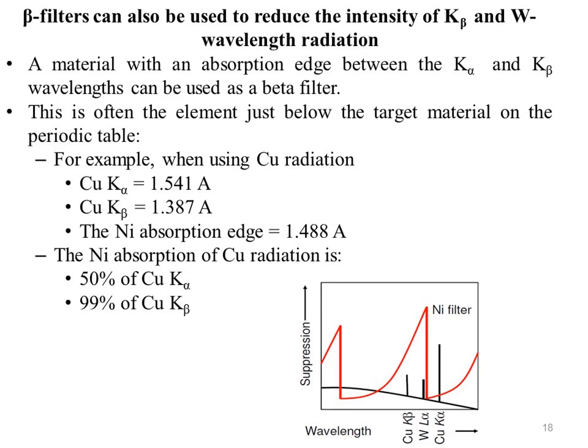Beta filters can also be used to reduce the intensity of K beta and white wavelength radiation, meaning tungsten wavelength radiation. A material with an absorption edge between the K alpha and K beta wavelengths can be used as a beta filter. This is often the element just below the target material on the periodic table. For example, when using copper radiation, copper K alpha is equal to 1.541 angstrom, copper K beta is 1.387 angstrom. The nickel absorption edge should be 1.488 angstrom.